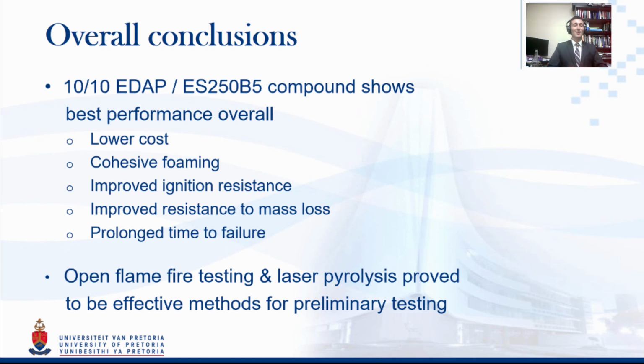So what we found here is that our best overall result was with the low temperature expandable graphite mixed with EDAP. This improves the cost, it causes cohesive foaming, improves ignition resistance, it improves the resistance to mass loss, prolongs the time to failure, and pretty much covers the entire board on the minor, small, and medium scale of the improvements we desired in our fire retardant compounds.